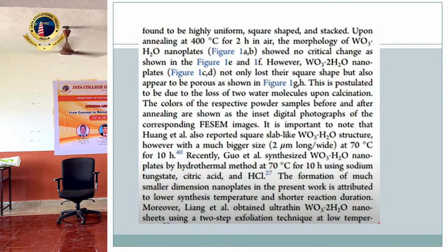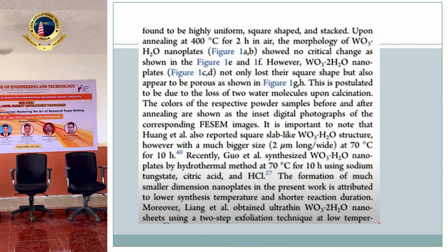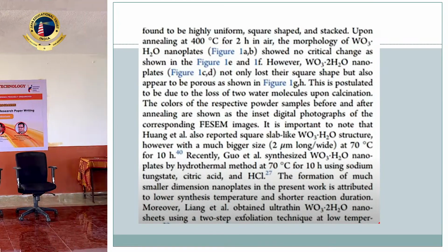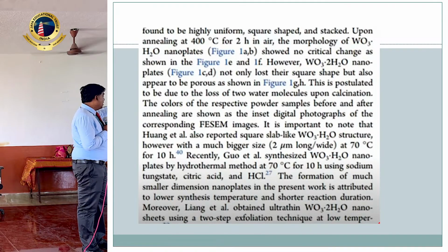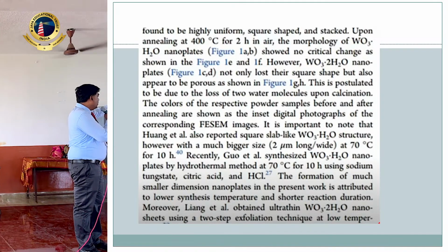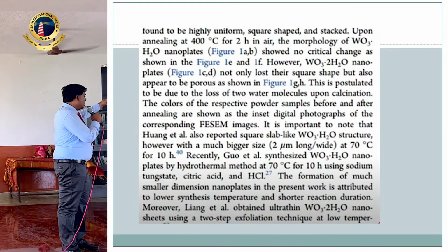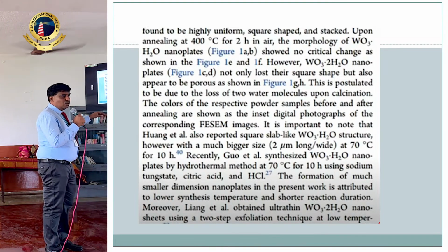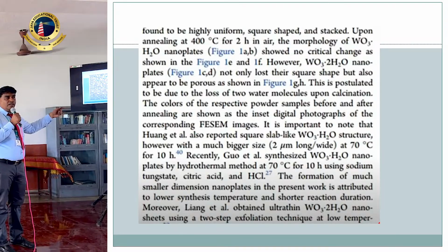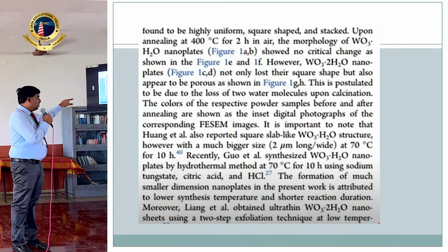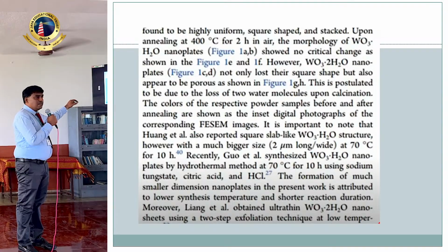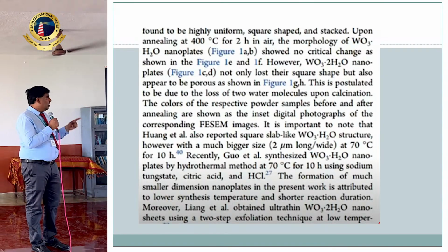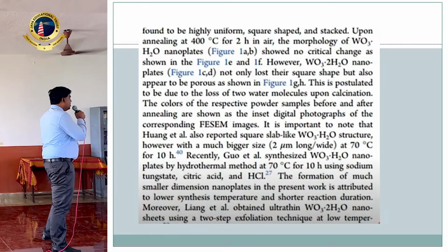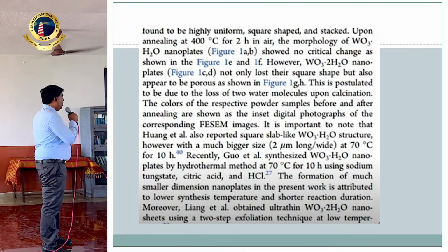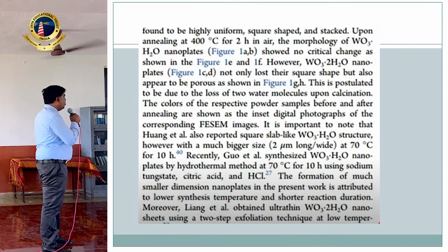So many others have worked on the same research area and found a different size of the nanoplates. But here, after comparison, they found the formation of much smaller dimension nanoplates in the present work. So many people have worked on the same area and observed that this present work has resulted in very fine nanoplates. For that they are justifying that the formation of much smaller dimension nanoplates in the present work is attributed to lower synthesis temperature and shorter reaction duration.